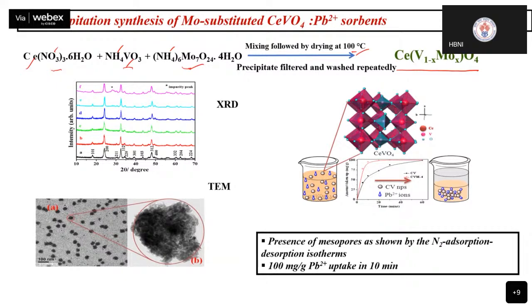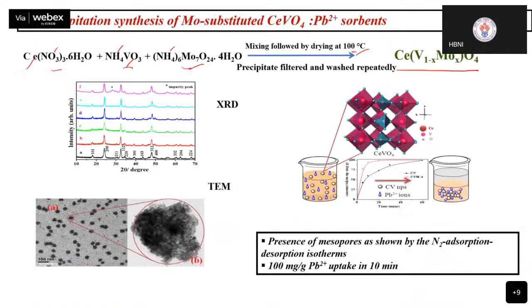In my case, I was lucky that I directly got this product. I did not have to heat it to obtain my final product. But heating and all, we call them the post-synthetic process, and sometimes they are necessary, sometimes they are not. So this gave me my product. Of course we did the XRDs and the TEM, and it gave us a very good lead sorbent which could take up 100 milligram of lead per gram of this material, in as little as 10 minutes. So a very simple synthesis.